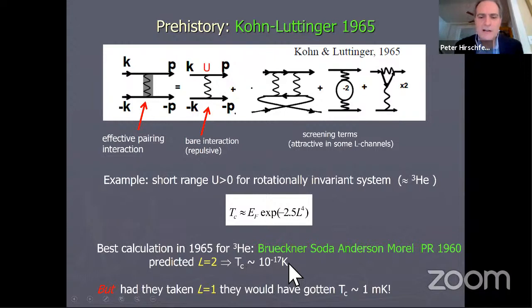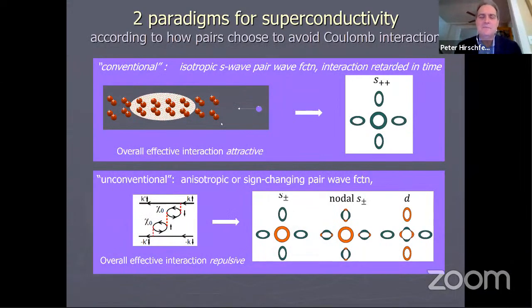So I remember when I was a graduate student, this was kind of a joke. When we were talking about heavy fermions, we knew it couldn't be Kohn-Luttinger because Tc was known to be very, very low. However, if they had just taken L equal 1 and inserted it not into this formula, because this is an asymptotic one, but into the correct formula that they found, they would have gotten Tc as 1 millikelvin, which is almost exactly the correct critical temperature for superfluid helium-3. So this is a very interesting and very provocative result, as it turns out.